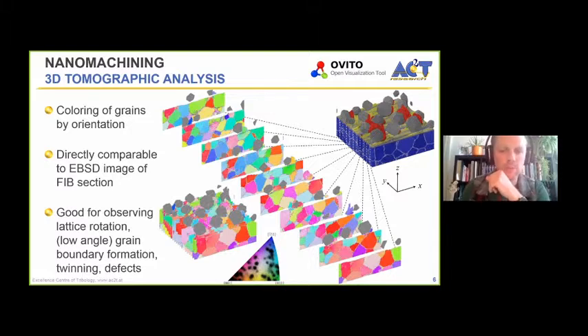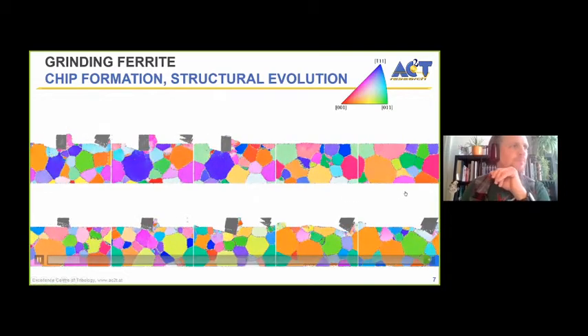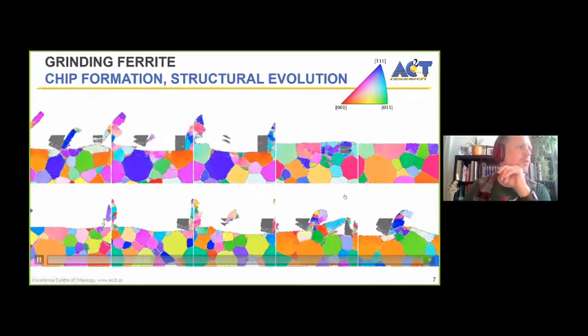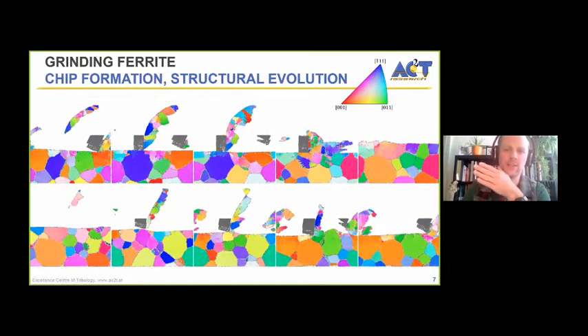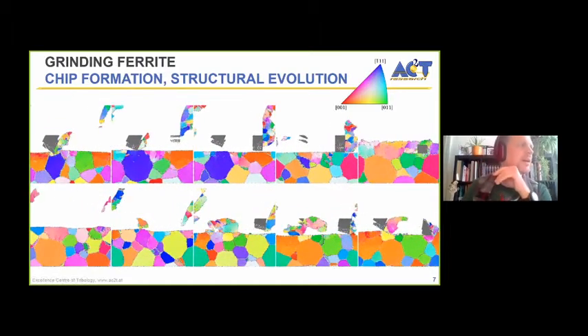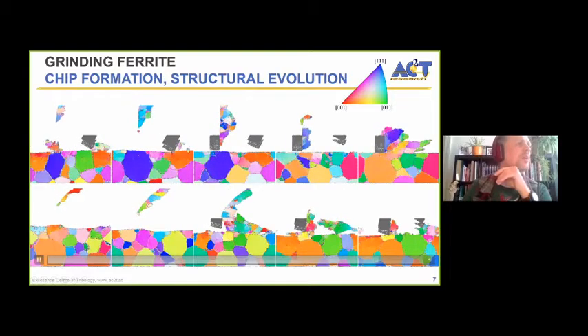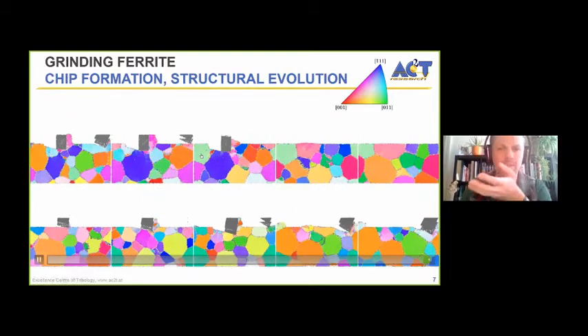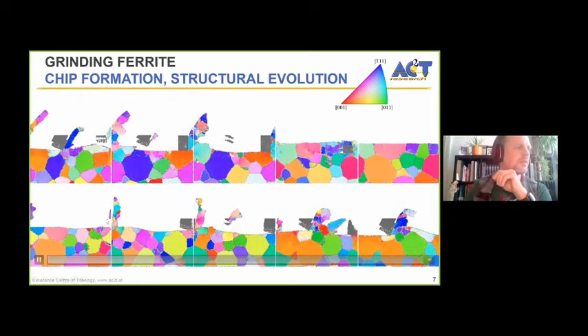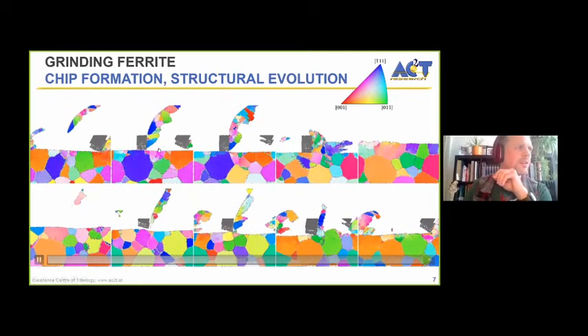So those are very popular with the material scientist crowd. And they are extremely good for observing phenomena like lattice rotation, the formation of grain boundaries, even low-angle grain boundaries. You can see twinning, you can see defects. The material scientists really feel at home with this. So if I look one step further, this would be a more recent example where 10 of these slices that are equally spaced through my system, where you see how the alumina abrasives basically cut a chip out of the workpiece. And you can take a look at chip morphology.